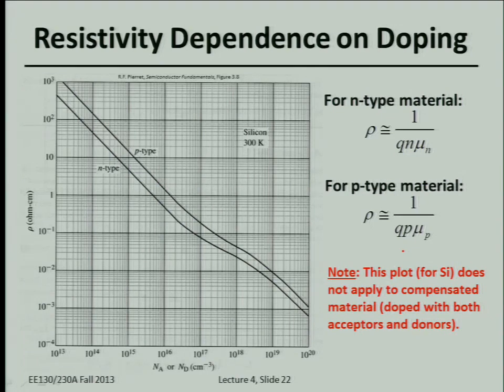Compensated material is material that's doped with both acceptors and donors. And compensated material is often encountered, let's say, in a MOSFET. The way we make this device is we start with maybe a P-type semiconductor wafer, or part of a semiconductor wafer, and then we selectively introduce, let's say, arsenic in these regions to form the source and drain conductive regions. So basically, these source and drain regions have both a heavily high dose of arsenic and some boron. So it's very common for a semiconductor sample to have dopants of both types, donors and acceptors.